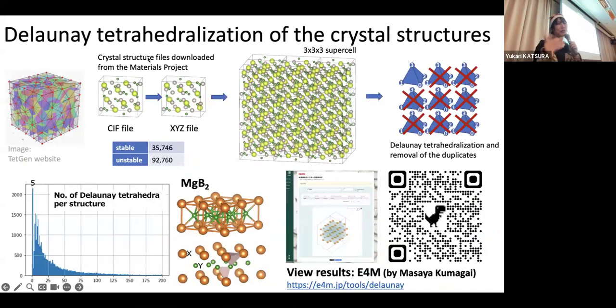So we carried out Delaunay tetrahedralization of the crystal structures. By giving the atomic coordinates, the program divides the space into tetrahedra like this. We collected these tetrahedra, removed the duplicates, and counted the number of different tetrahedra within the structure. The number of independent tetrahedra depends on the structure; some have only 1 or 2, and 5 was the most frequent number.